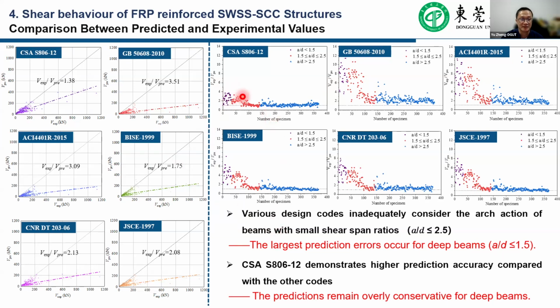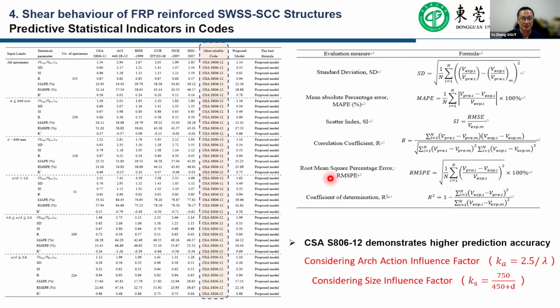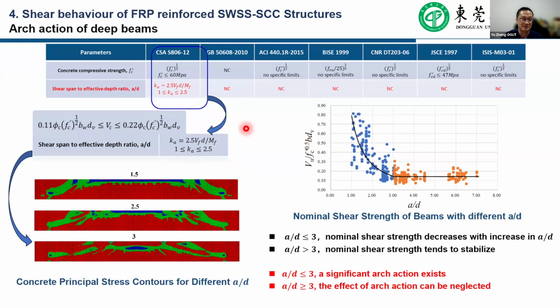Therefore, we can use those current design standards to predict the test results in our database. We can find that significant errors occur in the models with a small shear span ratio, especially for a span ratio smaller than 2.5. And we can find that compared to the other design codes, the CSA model shows a higher prediction accuracy, because the size effect and the arch action have been considered in that model. And therefore, we developed some statistical analysis, which is quite complicated, so we will not discuss it here. Based on the statistical analysis, we try to develop some modifications for the CSA model.